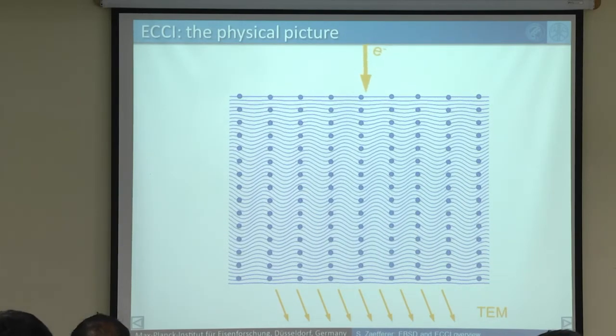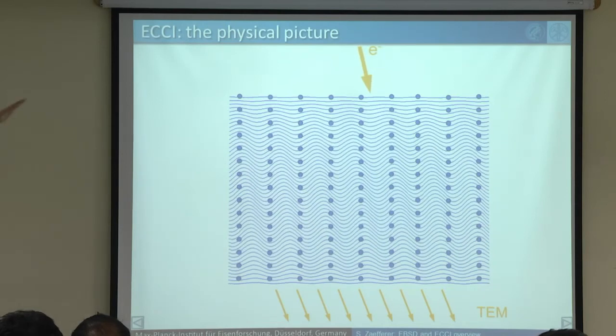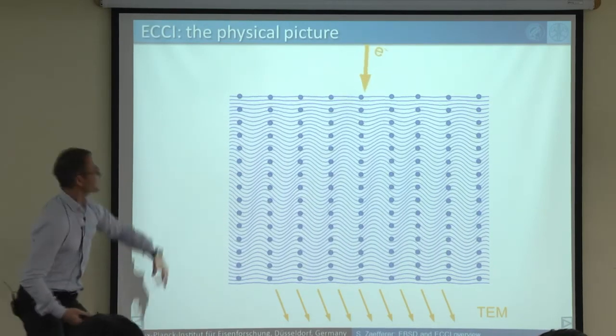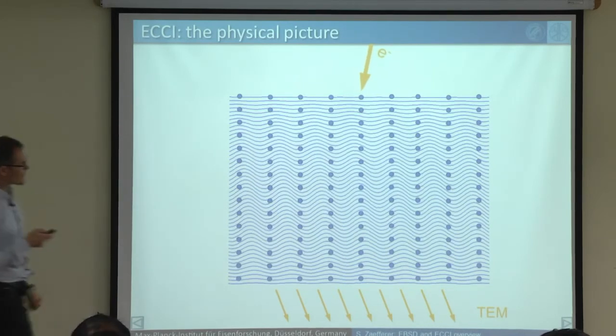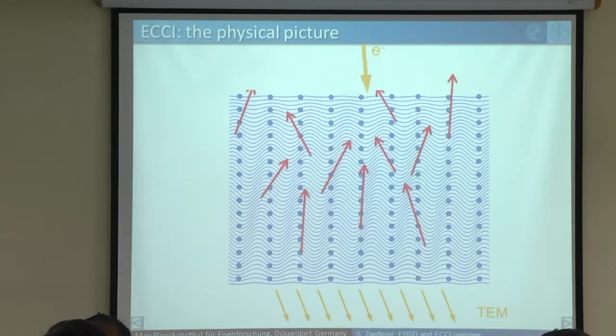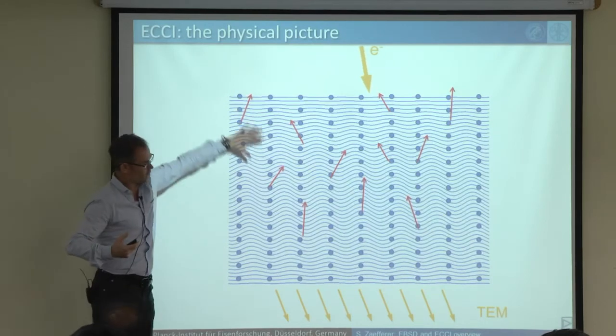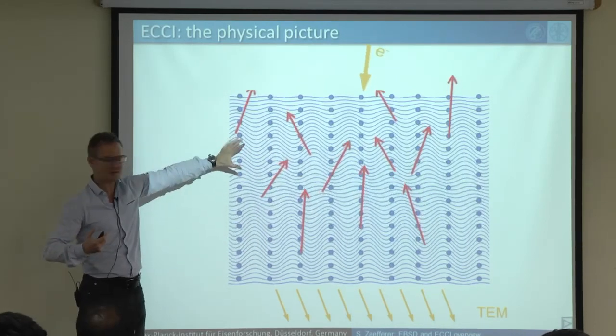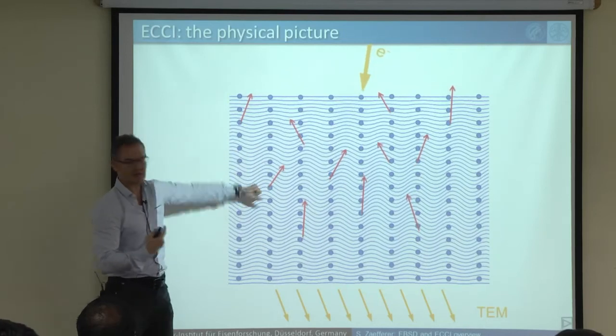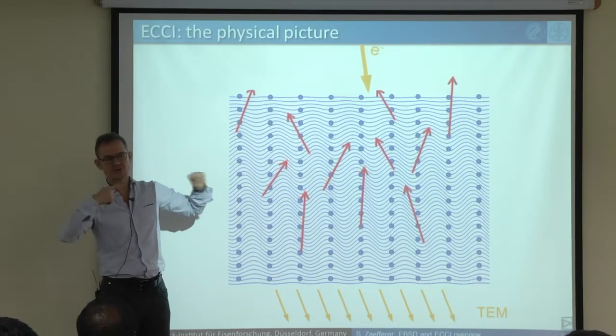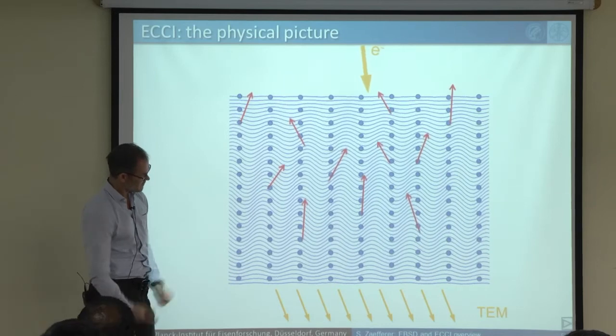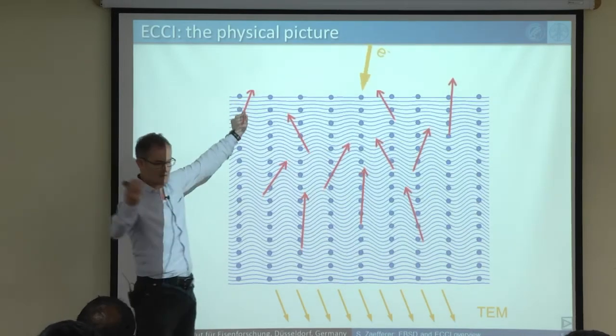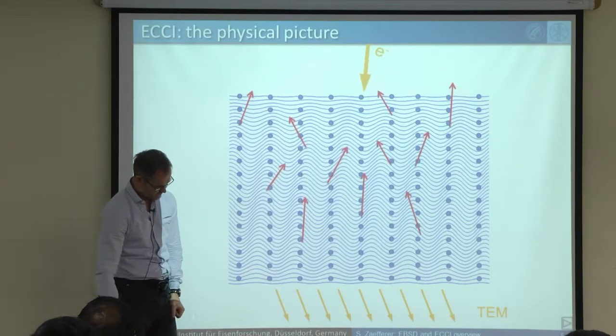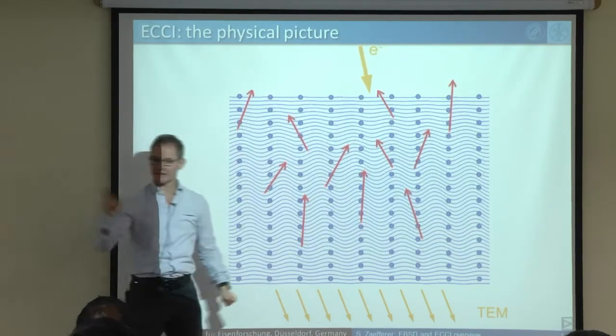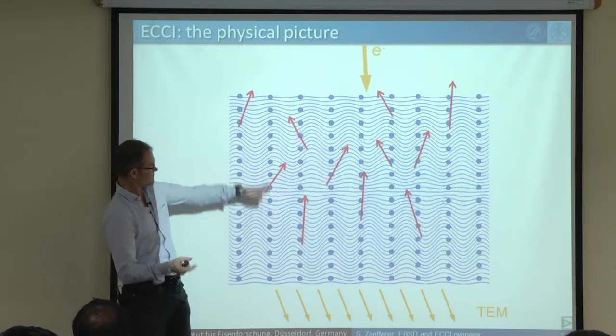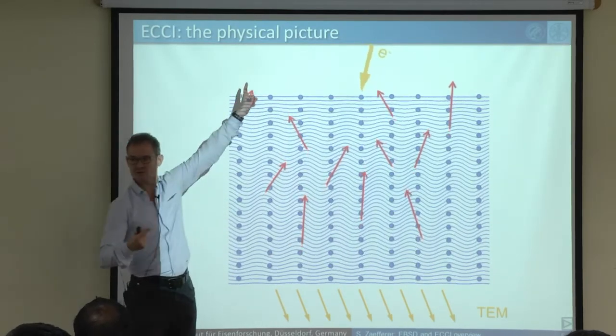Now, how do we see something in backscattering? Of course, we have an infinite sample. We cannot look below here. We can only look from the top. So what you have to consider is that these electrons, which are spreading through the sample, through the crystal, through the atomic structures, are interacting with the atoms. And they are not only doing Rutherford interaction, that means elastic interaction, which leads to diffraction, but they are also doing inelastic interaction. That means sometimes they hit a nucleus and are backscattered out of the sample.